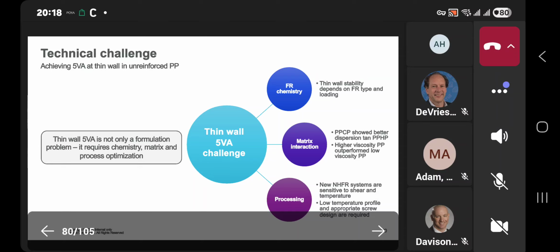Achieving 5VA in an unreinforced PP is not only a formulation problem, it is a combination of FR chemistry, matrix interaction, and processing. Internally, we saw that the thin wall stability depends on the FR type and loading. During our work, we saw that PP copolymer showed better dispersion than PP homopolymer, and that higher viscosity PP performed better than lower viscosity because of the dripping effect, of course.